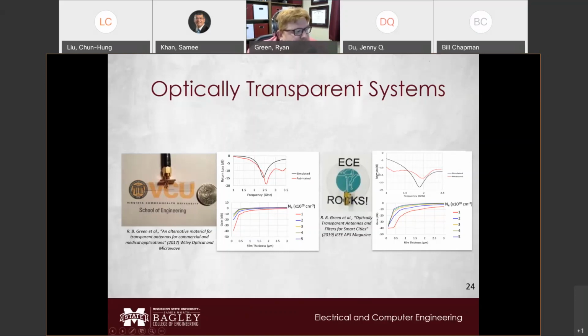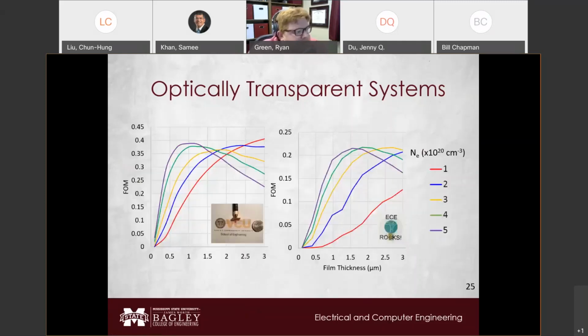And we saw a very similar result here with our hourglass antenna. And we said, well, this is interesting, so let's take a look at the figure of merit. What we found is that ultimately the efficiency of the antenna was so low due to these film thicknesses that our figure of merit just kept saying to increase the number of gallium atoms being doped into the system, increase your conductivity at the cost of transparency, because your efficiency was just that low. It was trying to counterbalance it. So we did not. We studied that.